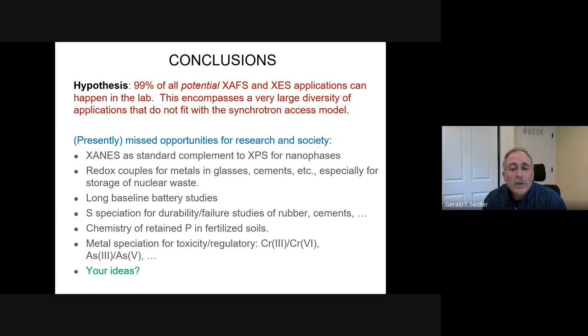It depends on the strength of absorption of the matrix that your metal is in. So if you have 1% platinum on a graphite support, such as is common for catalysts, that's not so bad at all. That's pretty easy because the carbon isn't absorbing at all at the energy for the platinum. On the other hand, if you're trying to study 1% iron doped into a cobalt oxide, then that's an awful lot harder because of the strong absorption from the cobalt at the iron energy. And so you really need to go and do the calculation for each specific system and figure out how strong the background absorption is.